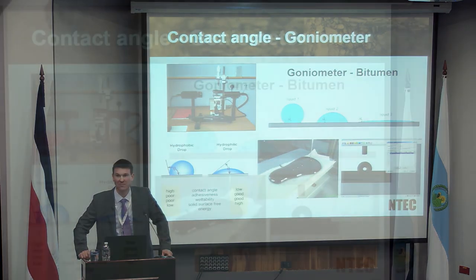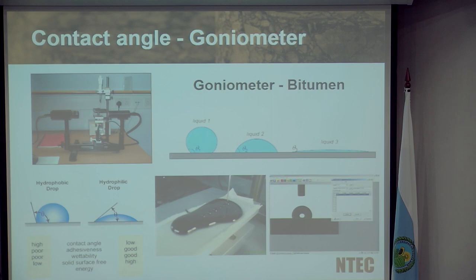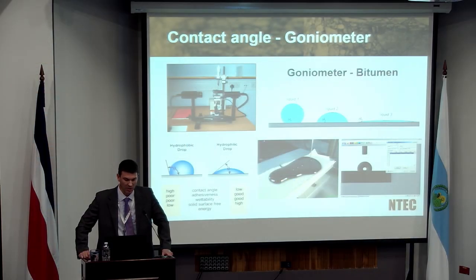A goniometer, very simply, is a very accurate image capturing device which allows you to measure, using image analysis, what your contact angle is. So again, if you take your glass slide, cover it in bitumen, and use different probe liquids on top of that solid bitumen glass plate, you can measure different contact angles. And this pretty much ranges. The bottom left-hand diagram shows you the two extremes, I guess, in terms of what you would normally find. Either a very hydrophobic type reaction between a liquid and the bitumen.